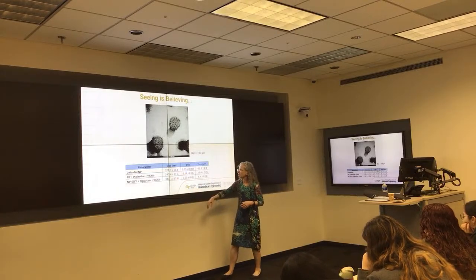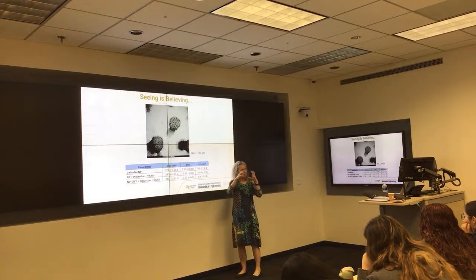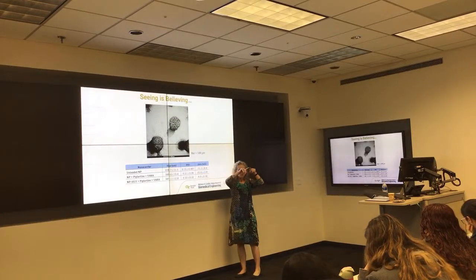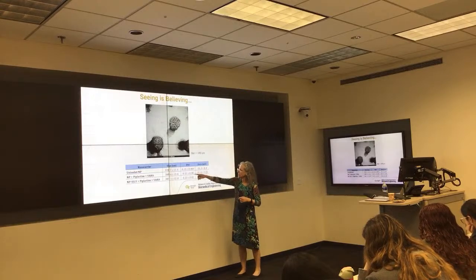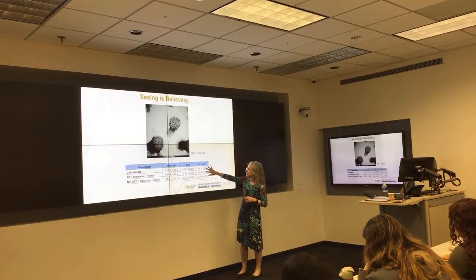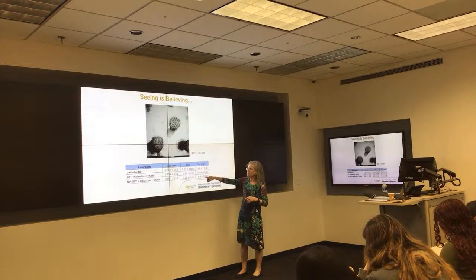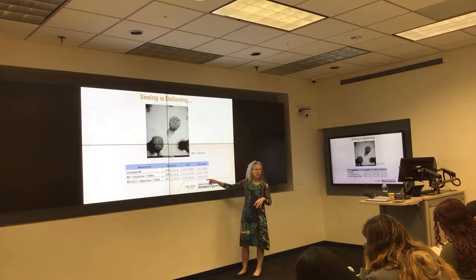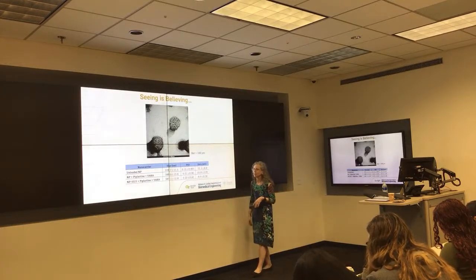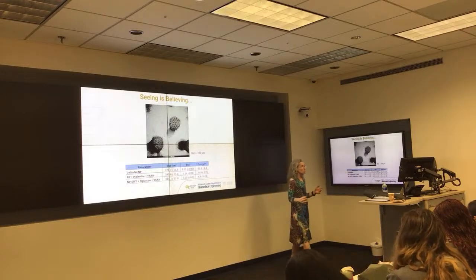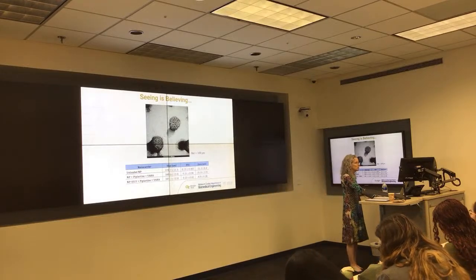They stay about the same size. The polydispersity of the particles changes a little bit, so the distribution of size broadens slightly. And the zeta potential is very negative without the collagen binding peptide. It drops to about -10, -9 with the collagen binding peptide. They still stay pretty stable though, so that's good.